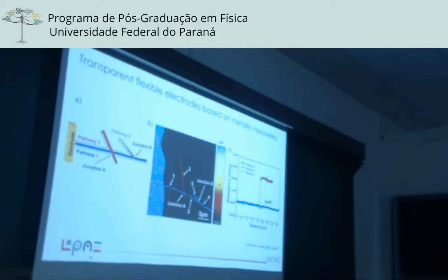And you see that this is the resistance, which means low resistance, high current, and now you see an increase of the resistivity, so low current over there on the red nanowire. This is what we have in the 3D rendering. We have the ITO, we have the nanowire, you see the other one, and these ones are not connected. They are present but not connected to the electrode. By playing with bending and mechanical strength, you can see the stability of this system.